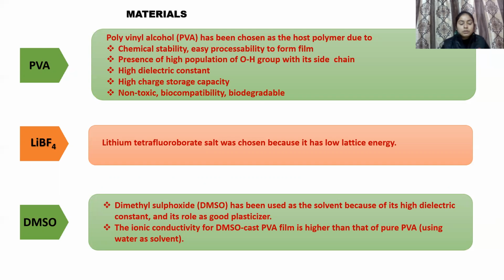Now, the materials used in my present work: PVA, polyvinyl alcohol, has been chosen as the host polymer in this work due to its chemical stability, easy processability to form film, presence of a high population of OH groups in its side chain, high dielectric constant, high charge storage capacity, and its non-toxic biocompatibility and biodegradability. The inorganic salt is LiBF4, lithium tetrafluoroborate, which has been chosen because of its low lattice energy. And DMSO, that is dimethyl